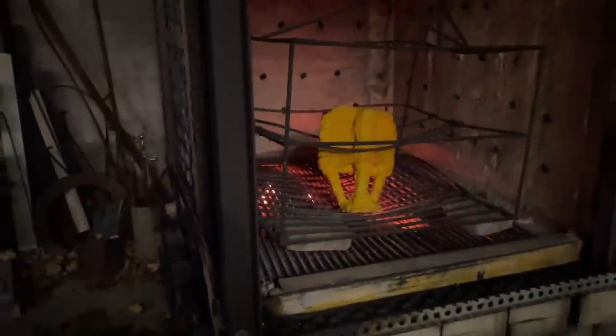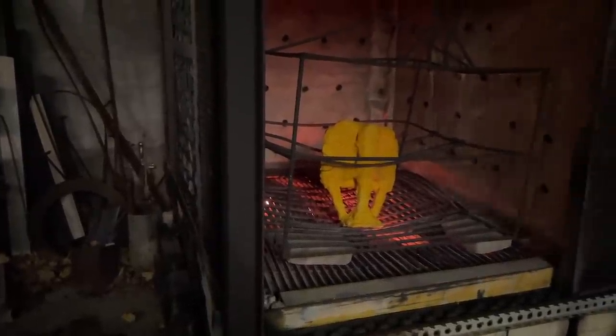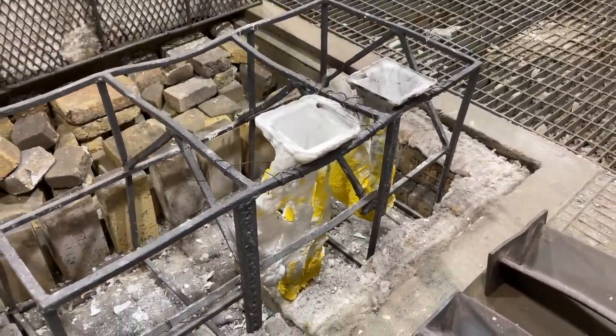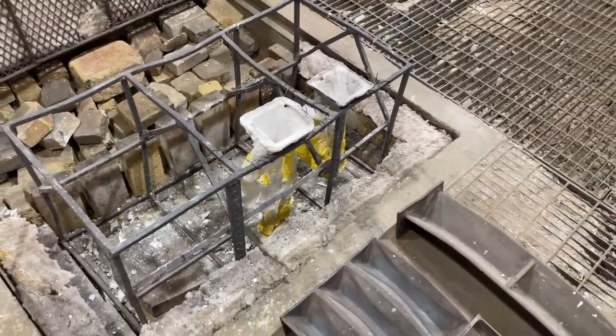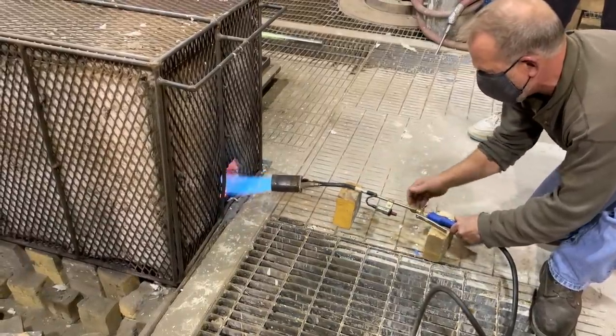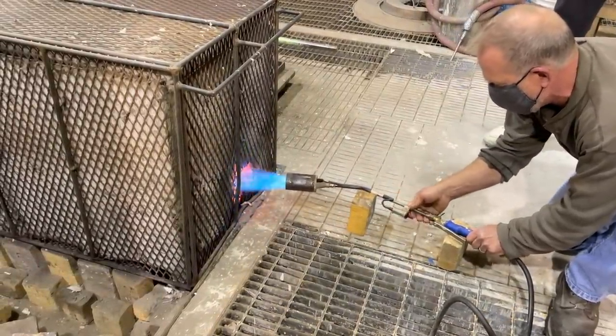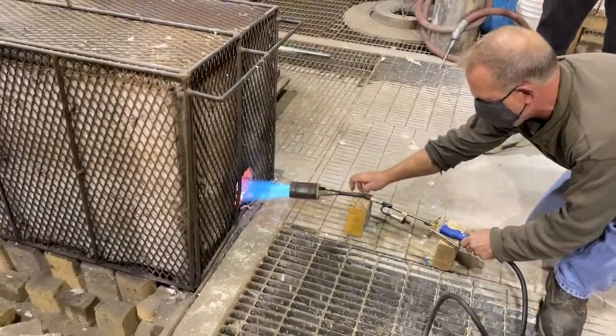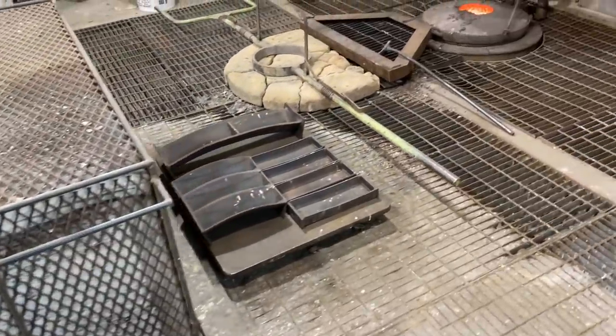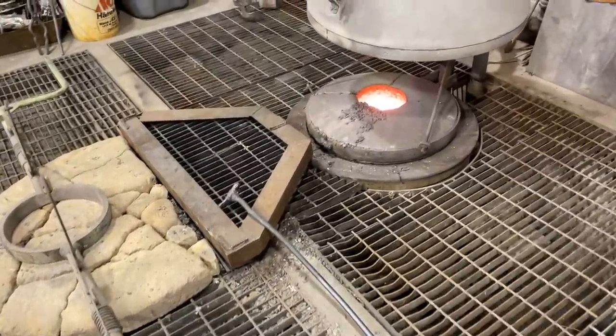At that point, the mold dries and we put it into a burnout kiln. We have that kiln about 1,000 degrees, and the wax kind of flash melts out of it, and then we leave it in for about an hour and a half, and that gets rid of all the carbon inside the ceramic shell mold. We bring the molds back into the foundry. We put them into a pouring cage, and we have a box cover that has Kaowool to keep it warm and preheat those molds while we're melting bronze so that they begin to kind of glow orange inside, about 1300 degrees or so the molds are. Meanwhile, we're heating the bronze in the furnace.